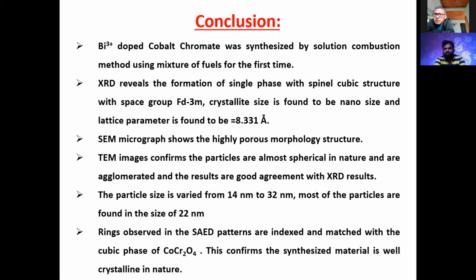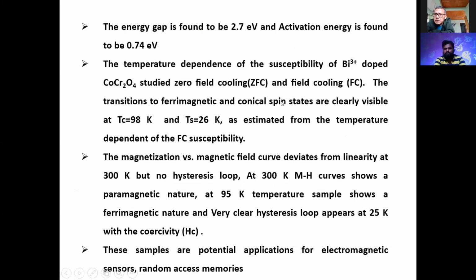The temperature dependent susceptibility of the cobalt chromate nanoparticles clearly shows two transitions, that is the ferrimagnetic transition and one more, the conical spiral transition. It is clearly visible at a critical temperature of 98 Kelvin, and the spiral transition phase occurred at 26 Kelvin. These both occur in the FC susceptibility and the MH loop.